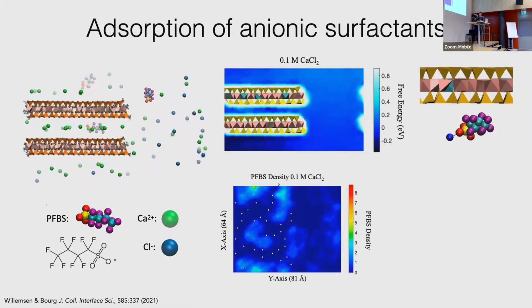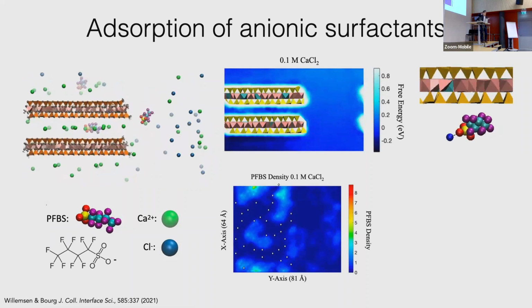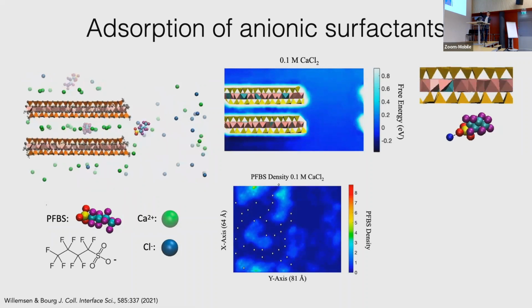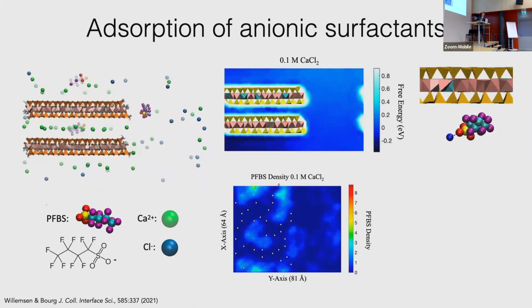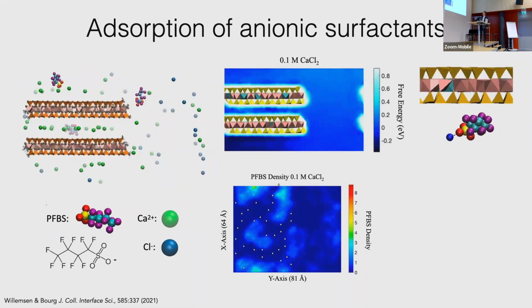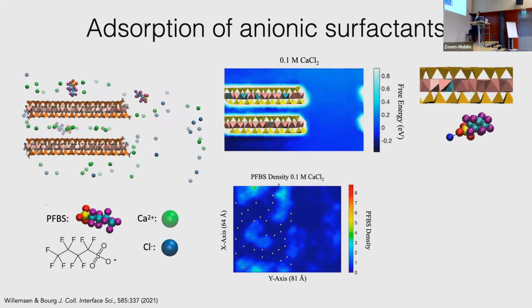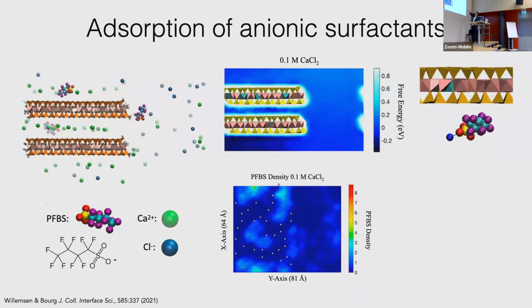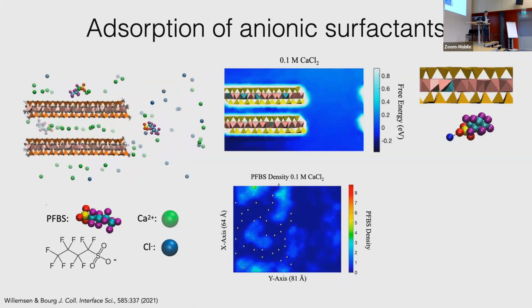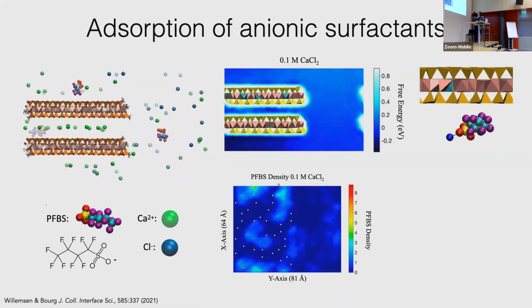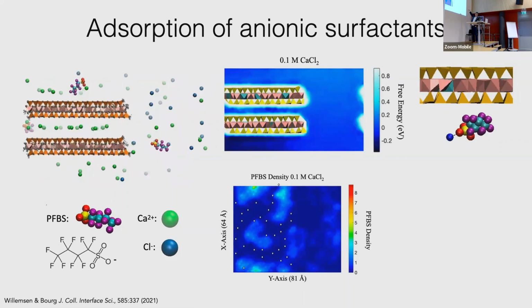Typically, when you have organic compounds with negative charge interacting with these negatively charged minerals, it's been hypothesized for a long time that the main binding mechanism is a cation bridging through a divalent cation that can bridge between the 2 negative charges. We're seeing some interaction with calciums. Actually, that's a calcium in green up there. But what we're seeing instead is that the PFAS compound is laying its fluorinated carbon tail on the uncharged parts of the surface, and it's turning its anionic head away from the surface to interact with an adsorbed cation.